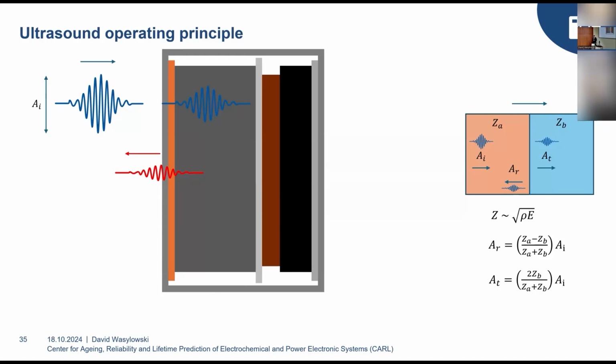And if we now introduce a deposit layer, so this aging effect that we saw earlier, we will again have this reflection in the beginning and end up with this transmitted wave. And if we now assume that this deposit has a slightly different acoustic impedance than the rest of the battery, we will actually get another reflection at this material interface between the battery materials and this deposit, further lowering the transmitted ultrasound wave from this initial gray sound wave to this blue one.